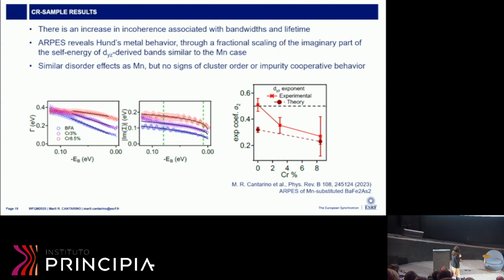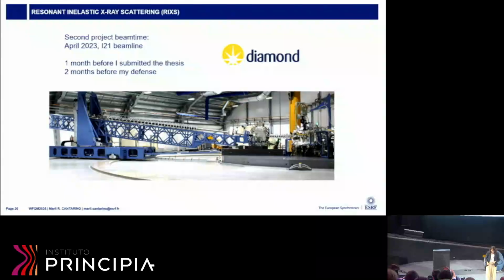We saw similar disorder effects as the manganese, with the bands getting broader. But we don't have any evidence from other works of signs of cluster order or impurity cooperative behavior in this case. So with chromium having the same spin as the iron, they're effectively perturbing the iron electronic states.